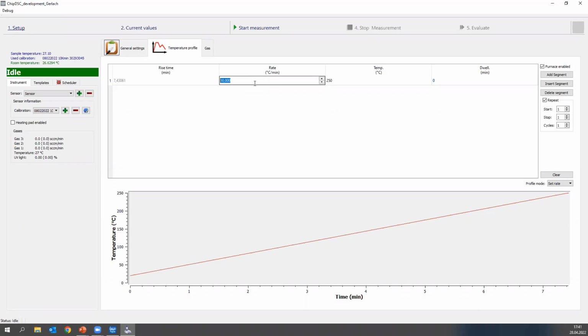This depends on the temperature range. If you just want to measure until 150 degrees, I would recommend 5 Kelvin because we need enough amplitude in our measurement here. It's limited, and of course the sample also has to follow the temperature profile, so the heating rate is a bit limited. Normally conventional DSC uses higher rates. This depends on the transition we want to check. But yeah, so this is a K value. So this will take around 29 minutes.